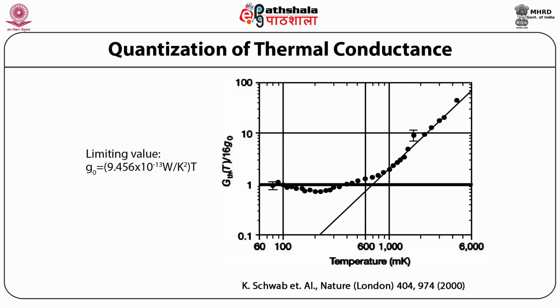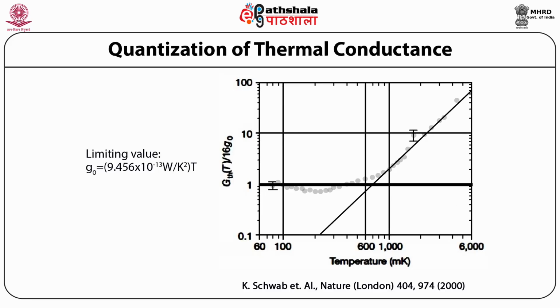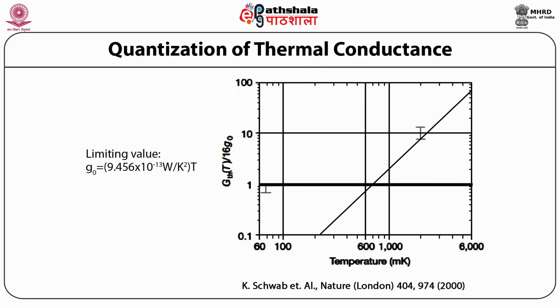A cubic power law behavior consistent with a mean free path of 0.9 µm is observed. For temperatures below T_CO, saturation in G_th at a value near the expected quantum of thermal conductance is observed.